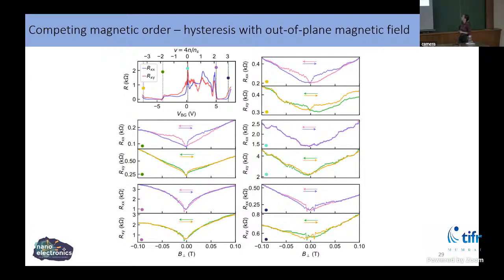Now, I also tried to study this hysteresis with an out-of-plane magnetic field. Indeed, you can see this hysteresis with an out-of-plane magnetic field, but it is not as prominent as with the in-plane magnetic field. These dots are just the biasing outside of the superconducting region, in the neighborhood of these superconducting regions. I studied the hysteresis of both the longitudinal as well as the transverse resistance, which shows some amount of hysteresis, but it's not very prominent, telling me that this magnetic order is perhaps more oriented towards the in-plane direction, some in-plane magnetic order.